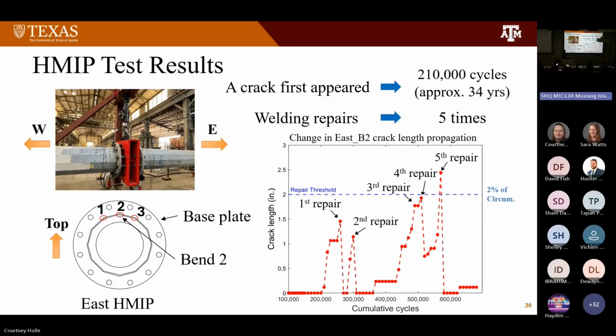For the first two repairs, welds were made immediately upon the rapid crack growth. After several attempts, we set our repair threshold at 2% of circumference. And this location has been repaired, and the crack reappeared for a total of 5 times.